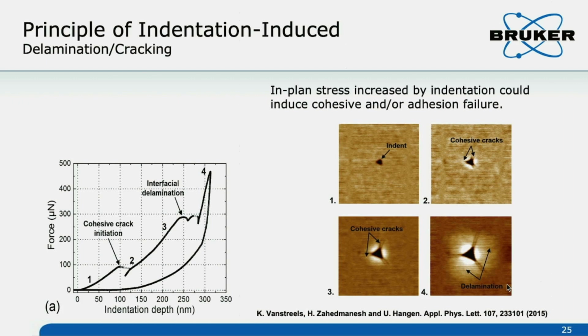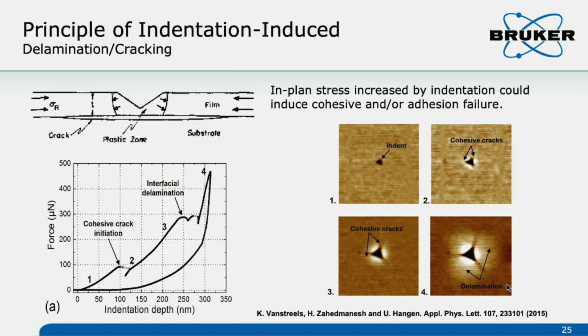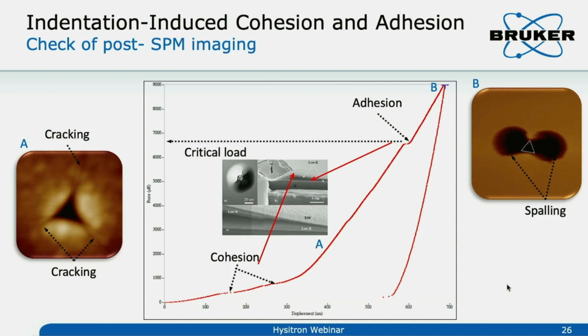Also, you see the cohesive crack and the crack growth by the penetration. Sometimes you see the delamination. You see, this is the film where delamination happened. Okay, so this is an example you can see more clearly. This is the data where we are using the indenter to indent into the thin film. You see the crack pop-in signal here, and you see the adhesion, right?